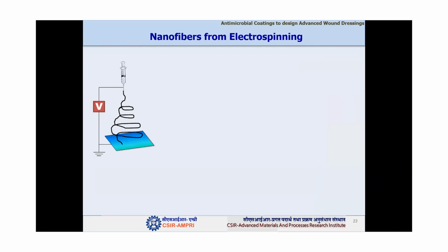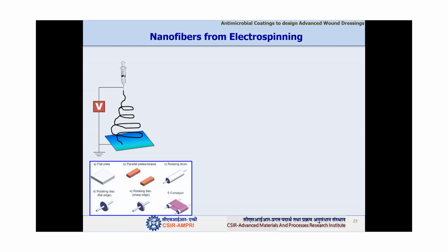First of all, I just want to give a brief idea of what electrospinning is. It is an electrohydrodynamic process in which we take a polymer solution in a syringe and apply a very high potential between the needle of the syringe and the substrate. Because of the high voltage, the polymer solution is stretched and splayed in the form of nanofibers, which are collected on the collector plate. The voltage involved is not just high, it is very high. Usually in electrospinning we use 12 kV to 30 kV. But the fibers you get using this technique are amazing.